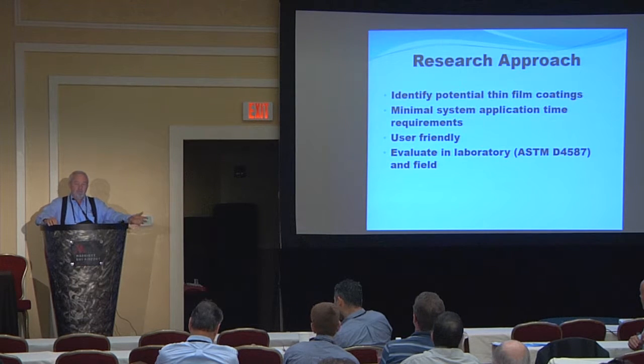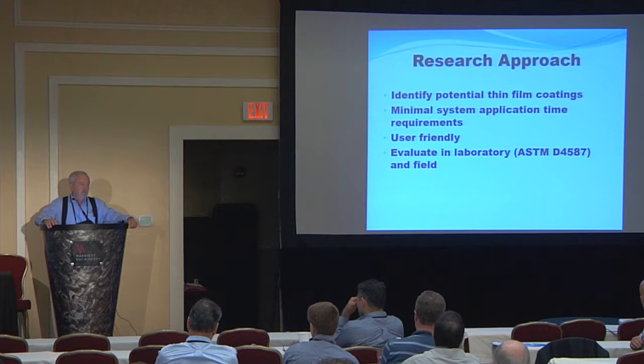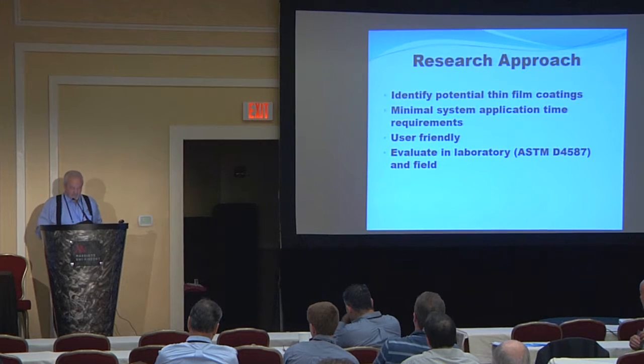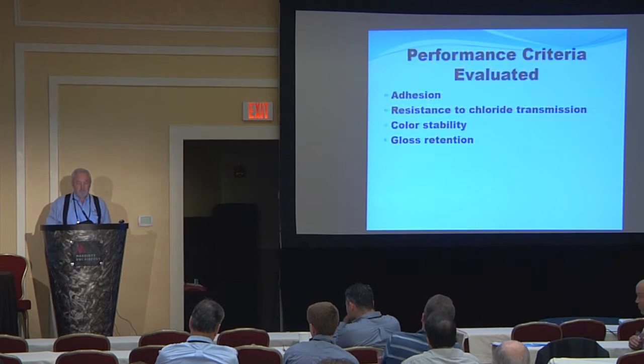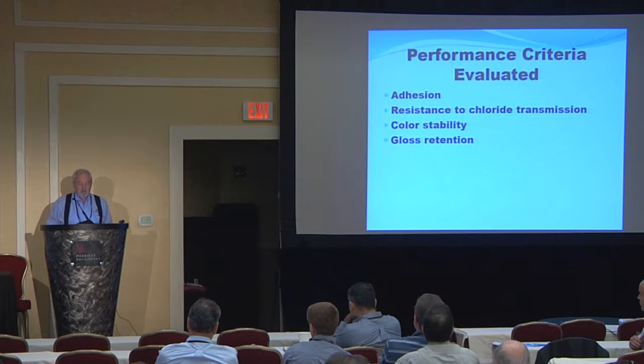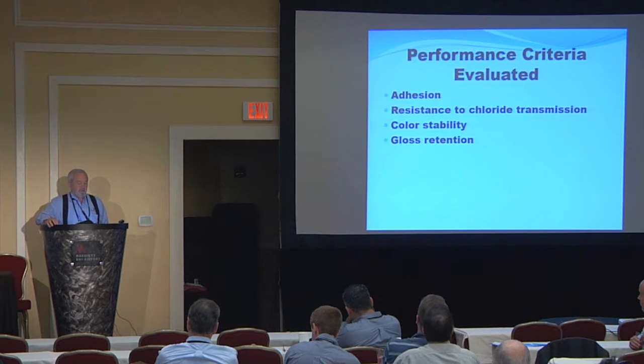In the laboratory, we did salt ponding tests and also ASTM D4587, which is the ultraviolet condensation weathering protocol. And then we evaluated various performance. The performance in particular that we were looking at was, first of all, adhesion of these thin film coatings to the concrete substrate, and the resistance of those coatings to chloride transmission. Thirdly, it was also color stability and gloss retention.